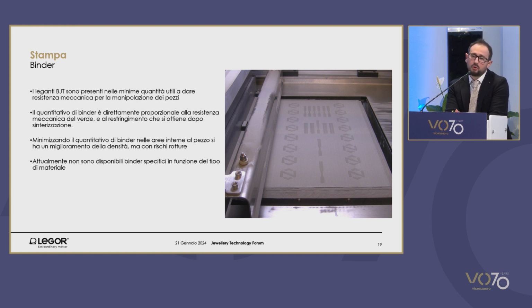The binder is a polymeric compound owned by the companies selling printers, and it guarantees the innermost adhesion of the powder particles during all low temperature phases. So it allows me to decide what is going to become an item and what is going to be reusable powder. The powder that remains in the machine is immediately ready for a second printing cycle. And the resistance of the green item depends on the quantity of binder.